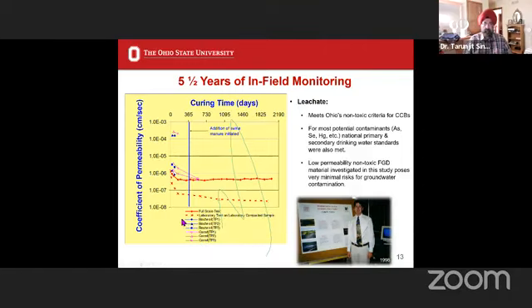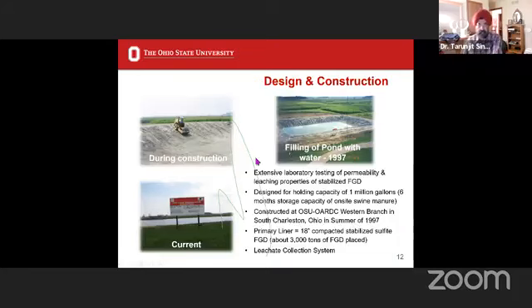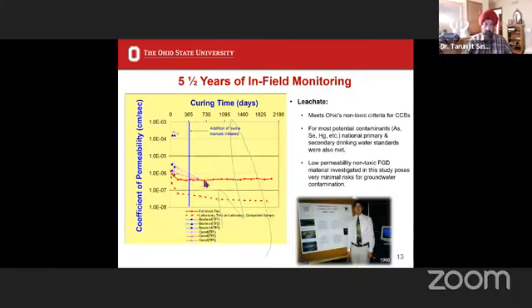And that is why our recommendation is this value. We were able to do the full scale tests because below this, we have a leachate collection system below which we have an impervious layer. So when we reduce the water level in here, the water in the pond remained constant. When we pumped it down, as this rose up in the sump, we had a falling head test, where the head difference between the two surfaces is reducing. And that is how we calculated the actual permeability of the full scale facility.